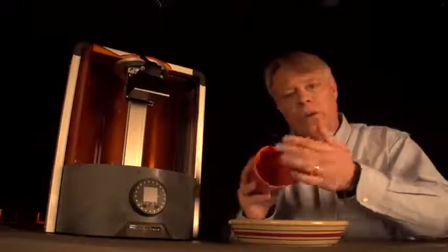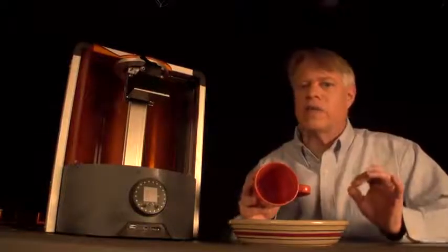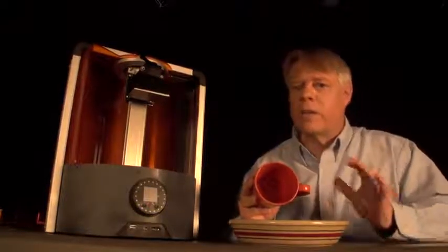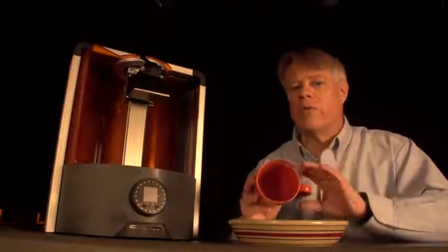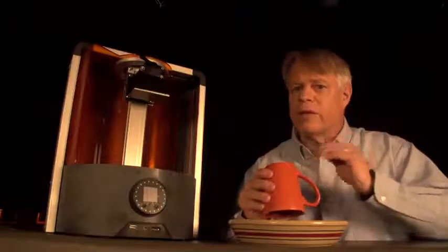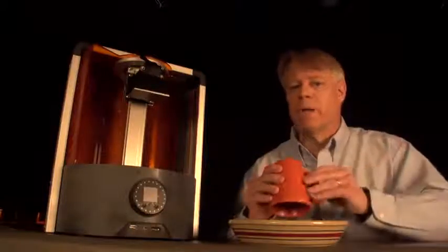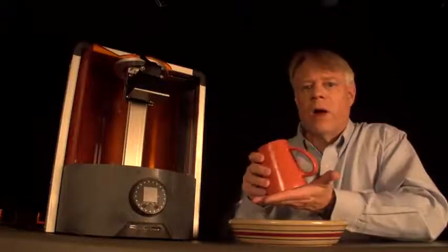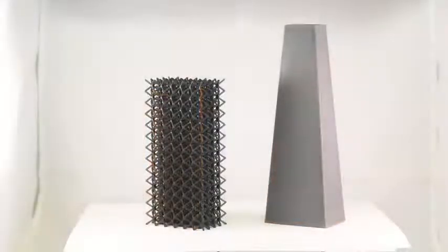In general, the force from pulling up scales as the fourth power of the radius of this opening, while sliding scales as the square of that radius. So, typically, sliding requires one hundredth the force of pulling up. And for this reason, this printer slides the tray to separate layer and printhead. Other printers peel the layer off with a rocking motion.